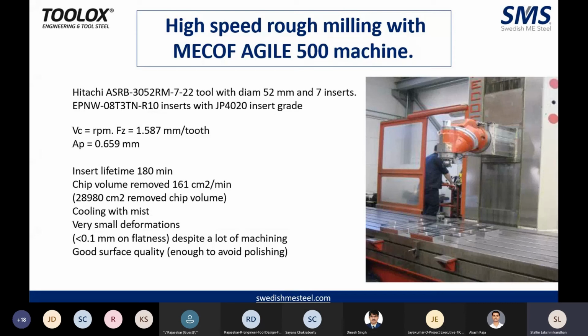So this is high-speed rough milling with an Agile 500 machine, which has been done. The insert which has been used had run around 180 minutes. The chip volume removed is 161 cubic centimeters per minute. As you can see, the total chip volume removed is around 30,000 cubic centimeters.